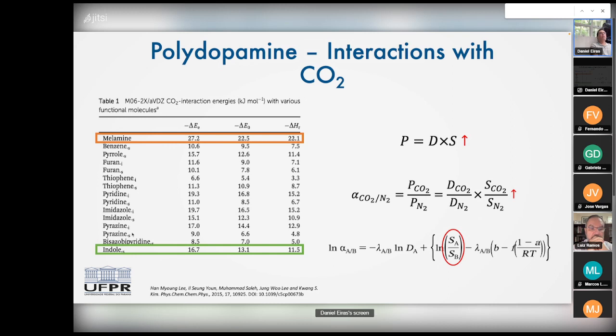So what I expect from this work was to increase the permeability and increase the selectivity by changing the parameter S, okay, the solubility coefficient, and also increase the selectivity due to solubility, which is the term S_CO2/S_nitrogen. Okay. With that, I could, at least in theory, increase both selectivity and permeability. So I would not reduce the permeability. I would skip the trade-off problem.